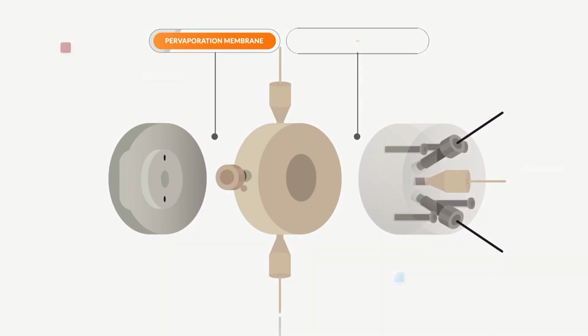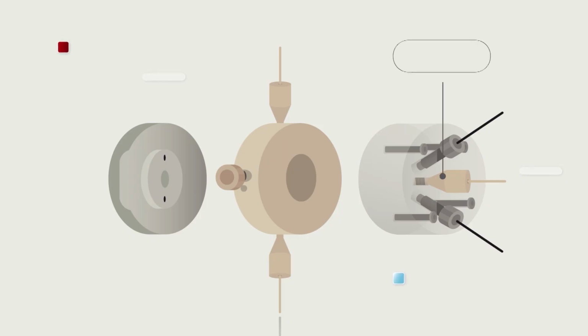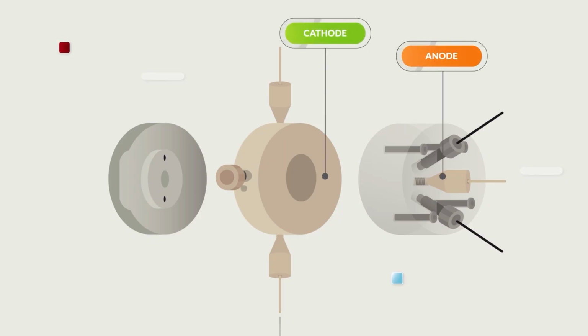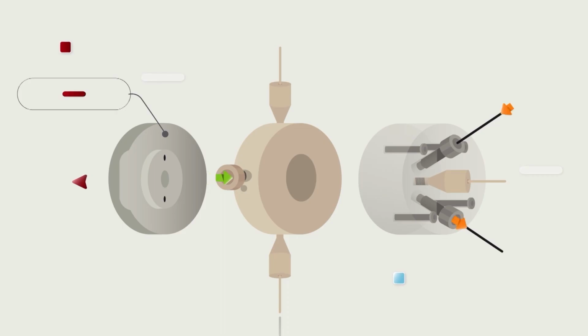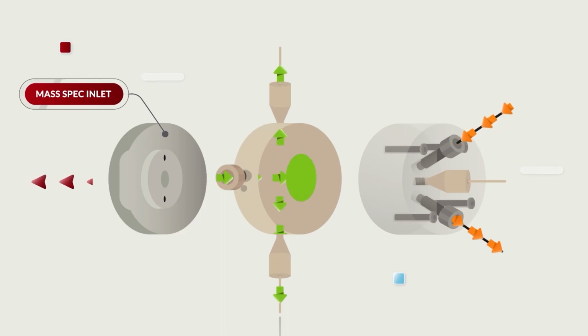We then have the type B cell, where the electrocatalyst of interest is separated from the pervaporation membrane and actually isolated into separate chambers. And this configuration is compatible with electrolyte flow. And so this cell configuration is really well suited for quantifying the activity of catalysts that need to be continuously supplied with reactant. And one example of such a reaction is electrochemical CO2 reduction. Furthermore, great care was taken in the design of the type B cell to ensure that the cell exhibits optimal electrochemical characteristics, such as a parallel potential field between the working and counter electrodes.